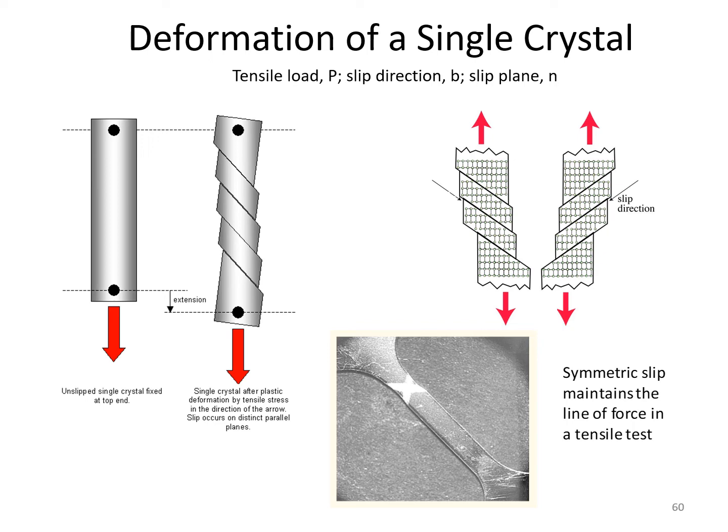in the material, until we get the operation of alternate slip systems to essentially bring the load line into parallel with the orientation of the specimen. This strain, if you can call it a strain, is of the order of less than 0.1% when you get to the yield point. So the yield point is typically anything between 200 and 600 MPa. And that can happen due to these constraints.